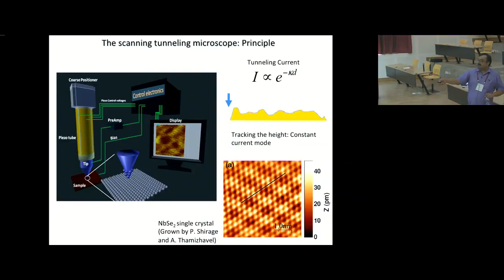When you track that, then you get the topography of the surface, and you can do it with atomic resolution. So this is an NbSe2 crystal on which you can see individual selenium atoms, and you can also see the contrast coming from the 3×3 charge density wave reconstruction.